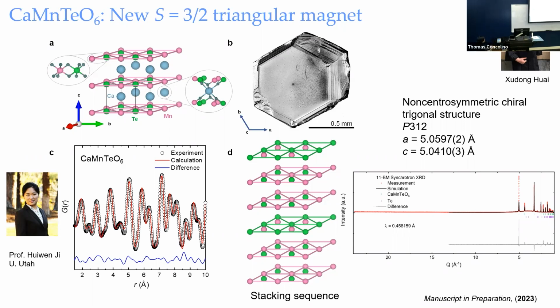But as you see, it's a layered, hexagonal plate crystal, but you see there's some stacking fault here, just looking at the pattern. And actually this is true. So you look at it again, it's a horrible fit, right? You look at the first peak here because of the preferred orientations. But the reason we think it's useful is because you can look and see whether we're missing the c-axis, whether the c-axis here is 3 times longer than what we presented. The answer to that is no, because if it was 3 times longer than that, we would have seen the first peak at a low angle, right?